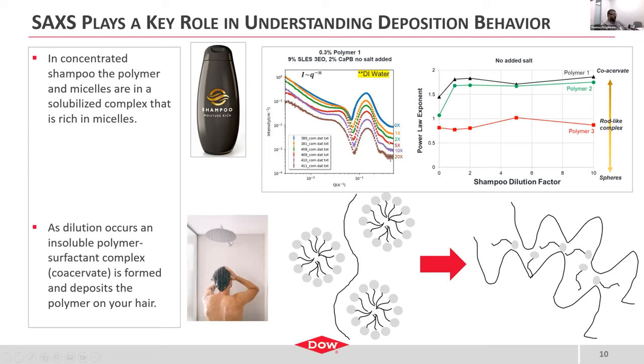We can use small angle X-ray scattering to identify the onset of coacervation in these sorts of systems, where we look at a standard surfactant composition of, you know, a sulfate and a CAPB type surfactant with the deposition polymer. And in the blue curve, that's the concentrated material. You see the scattering from the surfactant micelles. And then you see some scattering at a relatively low power law, at low Q, indicating the presence of a long-range structure like is shown in the center bottom there.